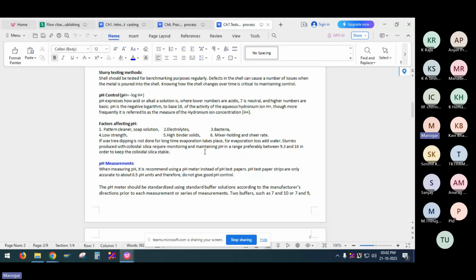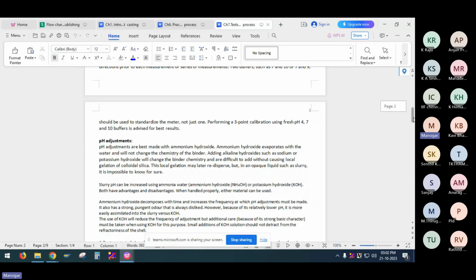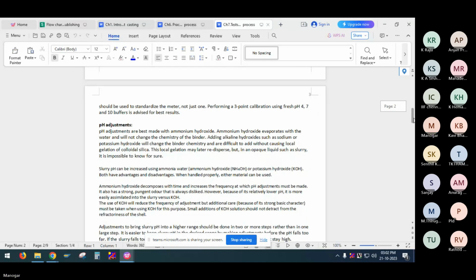Slurry is produced with the colloidal silica required, monitoring and maintaining pH in a range preferably between 9.3 to 10, so that you will get the stable colloidal silica. For pH measurement, it is suggested to use the pH meter instead of pH paper. And pH can be adjusted by using ammonium hydroxide or potassium hydroxide, but ammonium hydroxide is preferable. Both have advantages and disadvantages. When handled properly, either can be used.